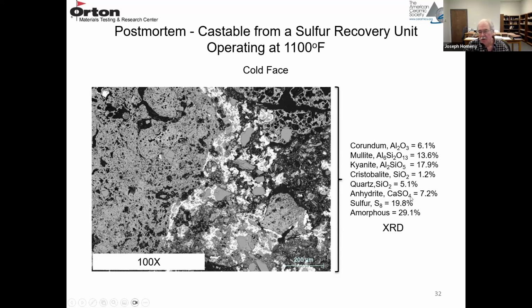There's calcium sulfate. So the sulfur has reacted with the lime in the calcium aluminate cement to form a calcium sulfate. There's elemental sulfur, quite a bit, 20%. And then an amorphous, probably a silicate glass of some type.